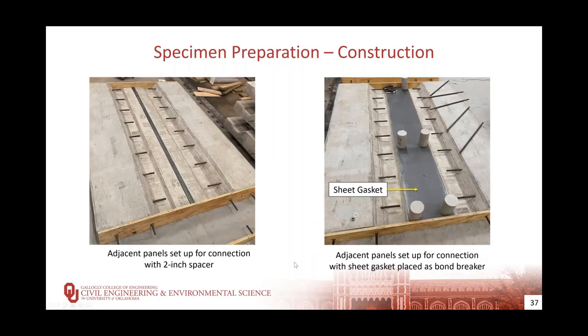To prepare for the connection pour, two panels were placed together with their openings facing each other. A 2-inch spacer was placed between the panels. The sheet gasket was cut and placed along the flat portions of the panel connection outline and gap. To make sure the gasket did not move during the pour, a small amount of silicone was applied to hold it in place. The bond breaker is seen in the photo on the right, weighed down by cylinders as the silicone cured.